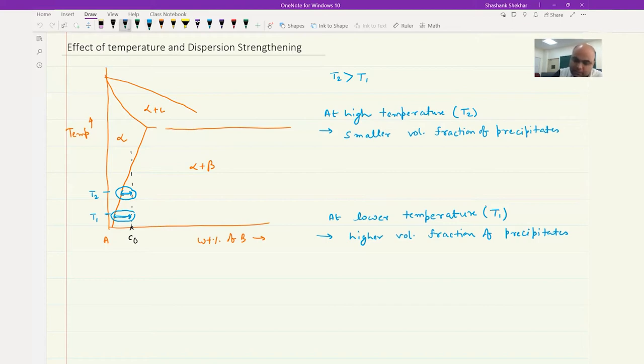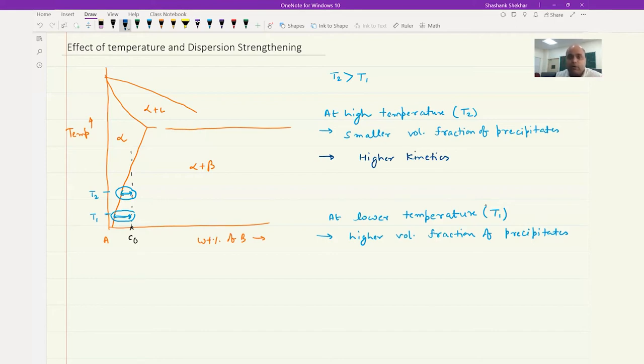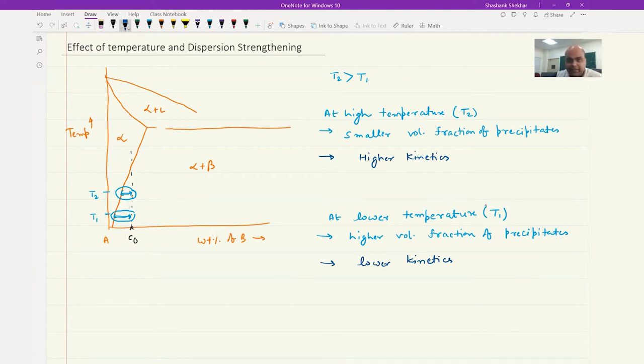Now the second point: at higher temperature, you have more driving force — diffusion is faster, meaning you have higher kinetics. It means the precipitates can form much earlier if you are at higher temperature. At lower temperature you have lower kinetics. So as you increase the temperature from T1 to T2, the kinetics also increases, meaning precipitate formation is going to be faster when the aging temperature is increased. This also means that the time to reach the peak hardness is shorter at higher temperature.